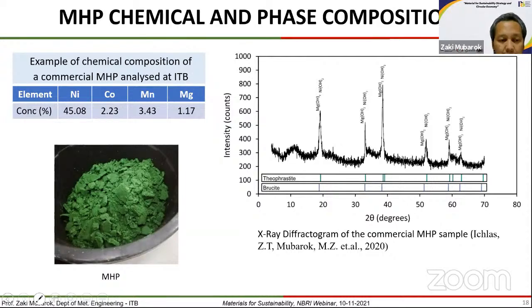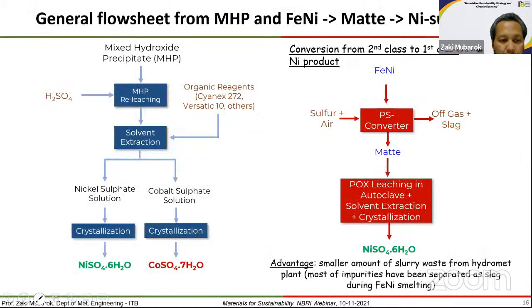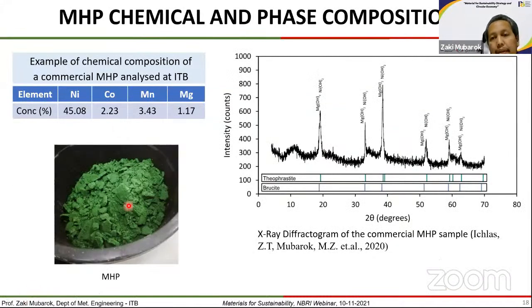I would like to present some of the results of our investigations. Our investigation on MHP, purification of MHP to nickel sulfate, started with the analysis of the chemical compositions. It contains 45% of nickel, 2% cobalt, 3% manganese, magnesium, and some other impurities, such as calcium, and perhaps also aluminum and chromium. And the XRD diffraction result is as follows. The phases present in MHP are nickel hydroxide and magnesium hydroxide.